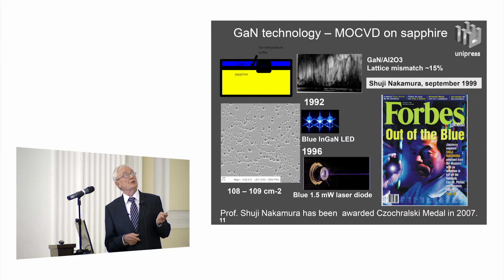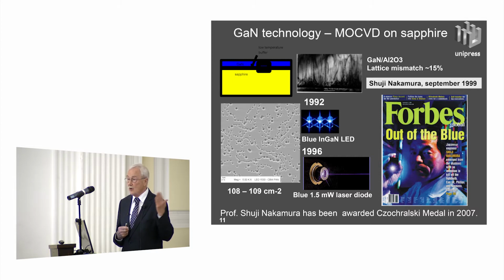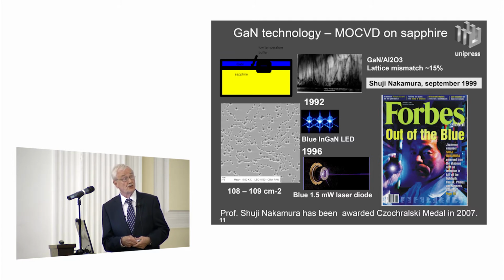And as a substrate, he used sapphire. The gallium nitride was not available, so he used sapphire. And his material had a lot of dislocations, a lot of defects. At this time, it was a real mystery why this material works, having such poor crystalline quality. However, it worked. Now it's better understood why it was working. But at this time, this was an enormous achievement of Shuji Nakamura. And Professor Shuji Nakamura was awarded the Czochralski Medal here at the same place in 2007.